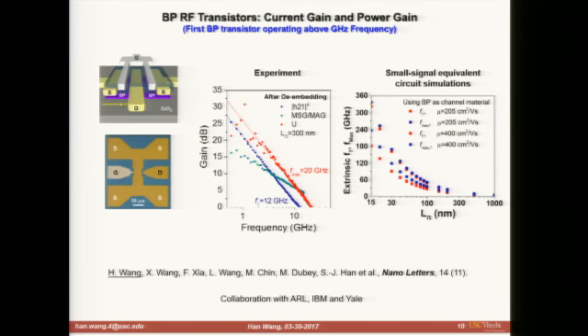Silicon devices perform similarly for a similar channel length of 300 nanometers. We also ran small signal equivalent circuit simulations to predict how far this material technology can bring us in terms of frequency performance in transistors. We predicted that if we can shrink the channel length down to about 30 nanometers, we can push both FT and Fmax above the 100 gigahertz mark.